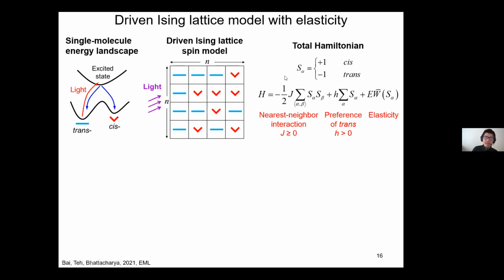This is a classical Ising model in many textbooks. So it has a nearest neighbor interaction, and it's a minus and J is positive. That means neighbor and neighbor really wants to stay with each other rather than be opposite. Okay, so they like to stay with each other in the same state. So trans likes trans, cis likes cis. So I have an external field by H. If H is positive, you can prove that it has a preference energetically of trans, which corresponds to here. But moreover, I will add an additional elasticity term, which I will talk to you later about.